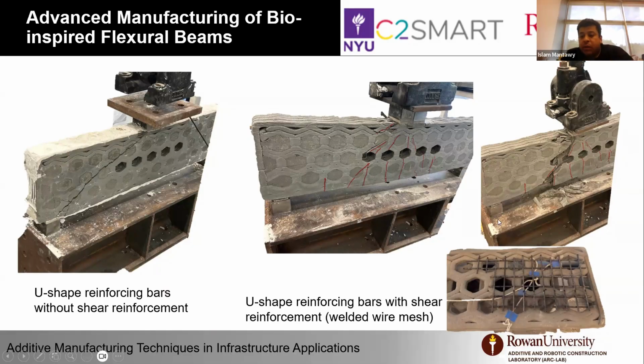which is what we did in future work, where we used another type of rigid welded wire mesh to place it during the prints. And here is an example of welded wire mesh that we used against a template. And here you can see that we were able to completely eliminate the shear cracks and activate flexure behavior, and we're able to get that behavior.